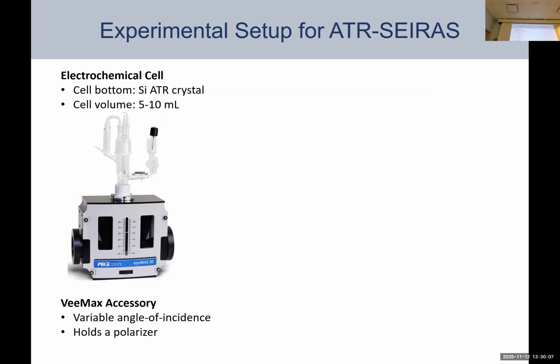Okay, additionally, we have this accessory at the top, which is an electrochemical cell. This is from Jackfish SEC. It's a Canadian company, actually. I'll show you a little bit more about them in a second. But essentially, buried inside this variable angle accessory is our silicon ATR crystal. And on top, bolted on via an O-ring, is the electrochemical cell. So you can put all of your counter and reference electrodes in here, fill it up with any electrolyte you want, and customize the rest of this aspect at will.